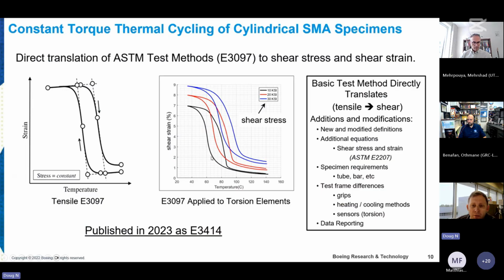And when you perform this test, you'll see that essentially the footprint of the response is the same. You generate hysteresis loops. You could take your four transformation temperatures off of these. You could generate them as a function of shear stress. There are a lot of details though associated with that translation. Anybody that does material testing here knows, it did take a few years to write this test method.